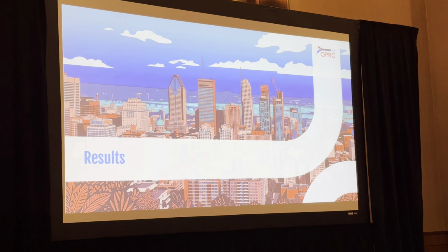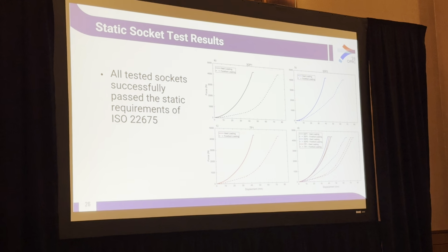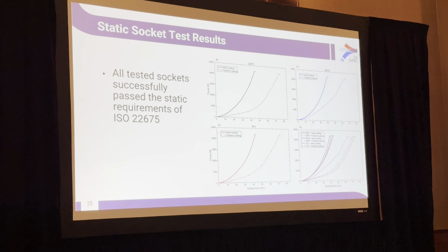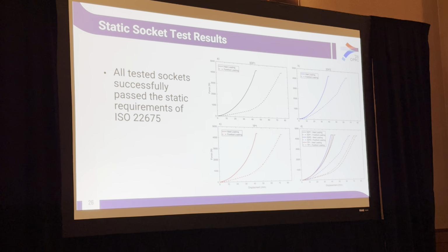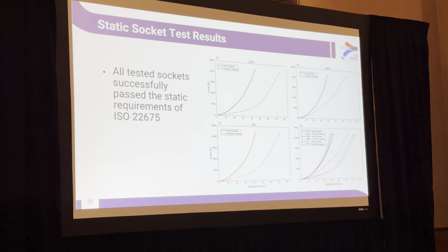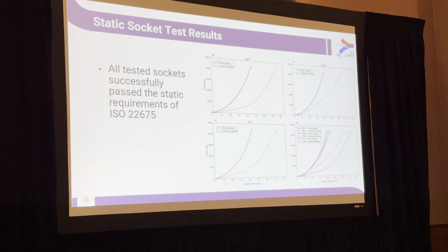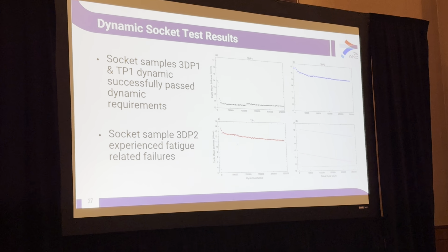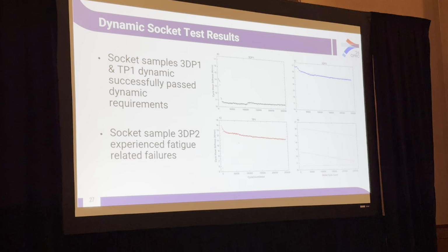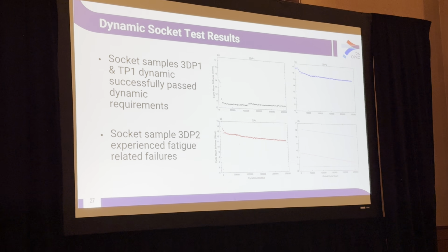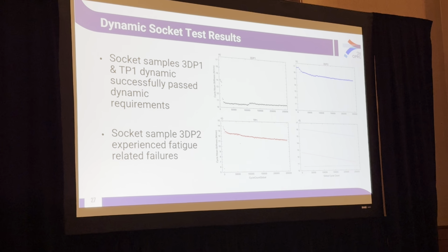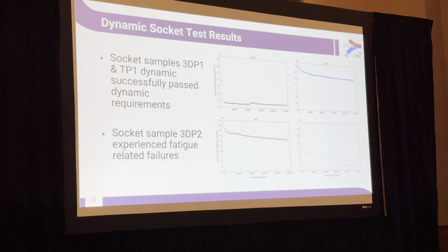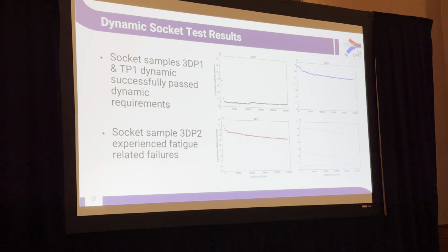So this brings us to the results of our socket testing. First of all, for our static results, all of the sockets withstood the required level of loading without any visible fractures or damage within the sockets. For our dynamic or cyclic testing, both sockets with geometry number 1, so the longer, more cylindrical limb shape, withstood the 250,000 cycles without any damage. However, our 3DP2 sample experienced fatigue-related failures within those 250,000 cycles.